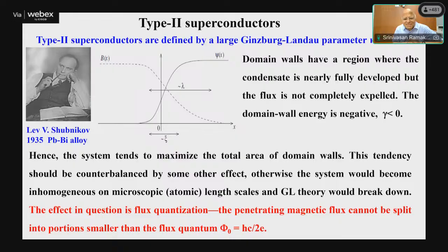This tendency should be counterbalanced by some other effect. Otherwise, the system will become inhomogeneous on an atomic or microscopic scale. So then the GL theory cannot be explained, because it completely becomes inhomogeneous. And for flux quantization, the penetrating magnetic field cannot split into proportions smaller than the flux quantum.